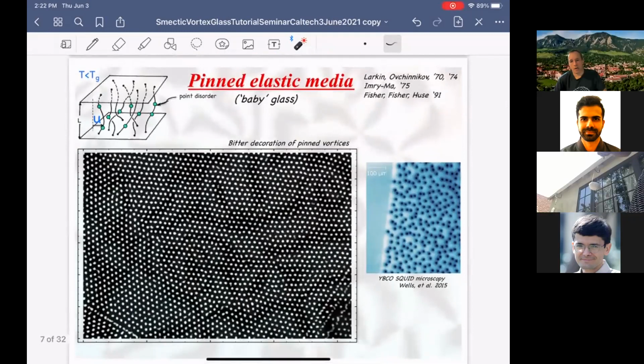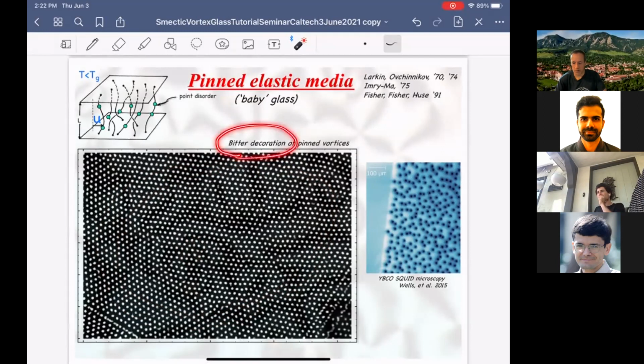So for completeness, you can image these vortices, and you can see here that in addition to local regions of crystallinity of a triangular lattice, you have all kinds of imperfections in your lattice, some vacancies and interstitials, lots of dislocations, grain boundaries, etc. So that's really how one can think about the intermediate or strong disorder limit: some kind of a structure like this, where you have a pinned medium. At short scales, it's crystalline, but at long scales, it's fully disordered, has dislocations, vacancies, interstitials, and grain boundaries. And these actual images, this is what's called the Bitter decoration image of vortices. And here's the SQUID image of vortices. Here it's far more disordered because this is in the film.